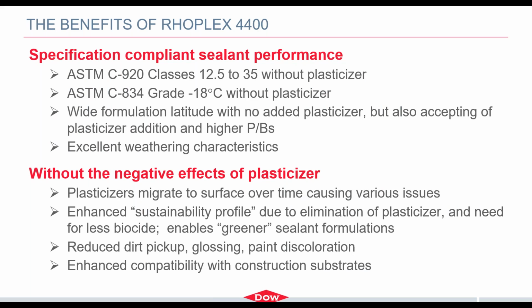So the benefits of 4400 are that it can be formulated over a wide formulation latitude to meet, for the customer to focus on performance versus cost. It can be formulated across the C920 specification, upwards of and including class 35, as well as ASTM C834 without the use of plasticizer. And I keep bringing up plasticizer because plasticizer has always been a common raw material used in formulating sealants. Even though one can formulate without plasticizer, it also is accepting of low levels of plasticizer to target higher P to B ratios, and it has excellent weathering characteristics.